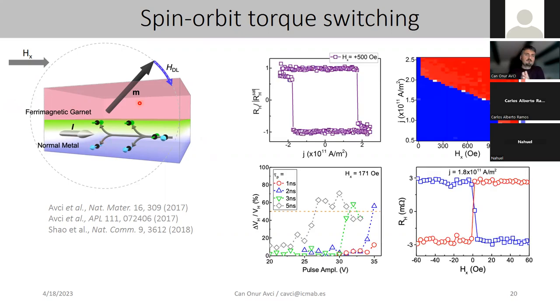That's the very same paper that I showed during the previous slide. We also showed that we can switch the magnetization with current densities on the order of 10 to the 11 amps per meter squared in the presence of an in-plane field, because that in-plane field is required to break the rotational symmetry of the damping-like effective field.